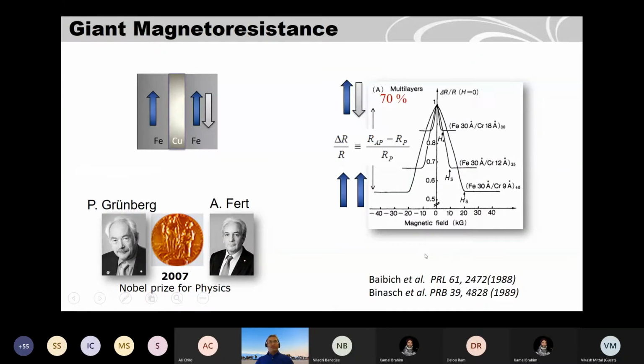So what is giant magnetoresistance? Maybe most of you know this already. Let me just put it in simple words: when you have two ferromagnets separated by a thin layer of metal, depending upon the orientation of these two magnets, electrons can either pass through or reflect. When they are parallel, electrons can pass through, and the resistance is low. When they are antiparallel, the resistance will be higher because electrons have to reflect back. So they saw this resistance change when they applied a magnetic field to make it parallel and antiparallel. And these are actually iron chromium multilayers.